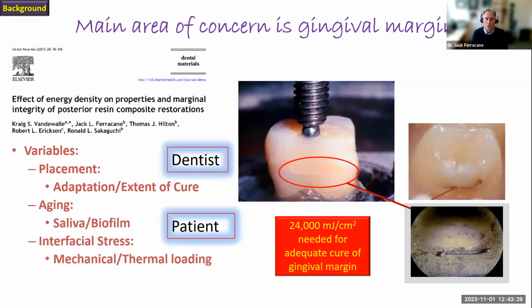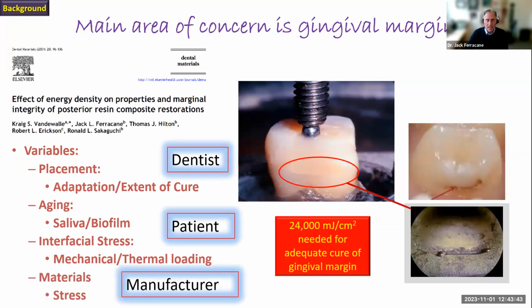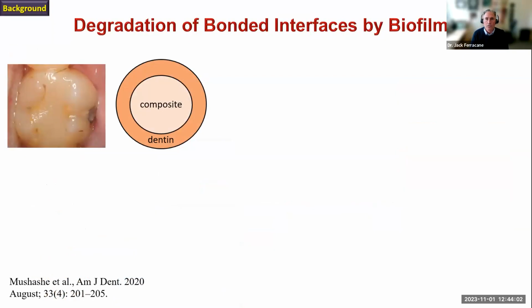The patient also has a role in this because they have saliva, they form biofilms on these restorations, and they age with time. And they are the ones responsible for interfacial stresses due to mechanical forces or due to thermal loading. And then the materials themselves, which are produced by the manufacturer. And in part, we think the debonding may be a function of the stress that's produced in the material during curing. And this is all a part of the manufacturing process and the formulation of the material. So everybody has a role essentially in how well this restoration does or does not do.